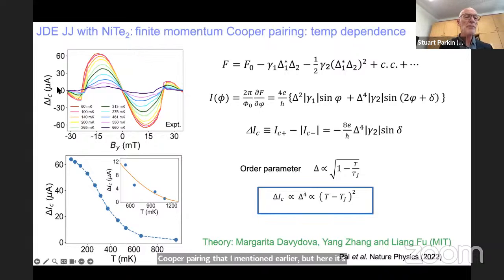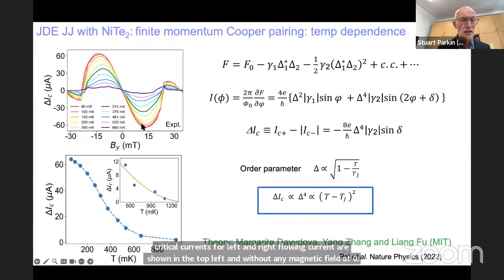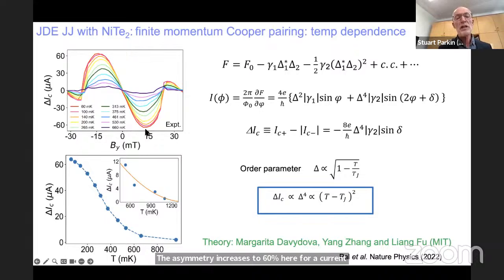And interestingly, if we look at the asymmetry in the critical currents for left and right flowing current, as shown in the top left, without any magnetic field, it's 0. The asymmetry increases to 60% here for a field of a few millitesla, but with further increase in field, it decreases. It changes sign and then will continue to oscillate. And this oscillation is due to the oscillatory nature of the phase difference between the two niobium electrodes. And this is due to, we think, second order Cooper pair tunneling.